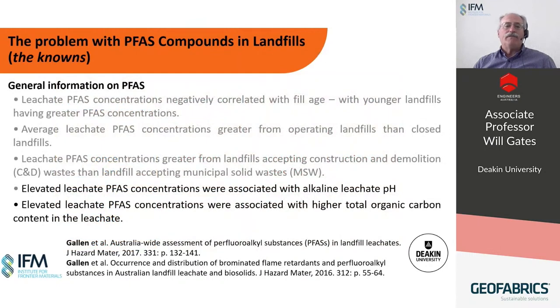Other important findings from these reports show that the associated chemistry of leachate is highly relevant for impacting PFAS migration. In other words, a high pH of leachate ensures that the ionic form of the PFAS dominates. If there's a high organic carbon loading in the leachate, either in the form of dissolved organic matter or in particulate organic matter, then that will enhance the PFAS loading in the leachate.